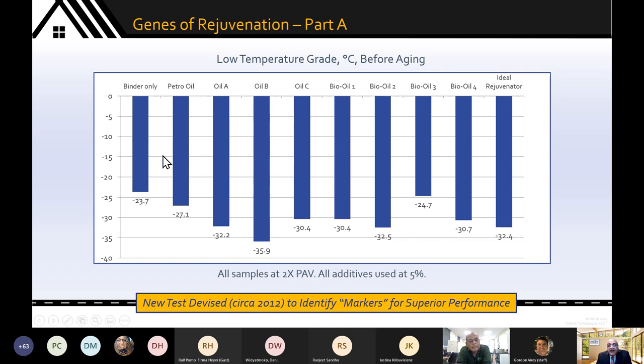So we took virgin binder, we aged it artificially in the lab, PAV aged it to produce synthetic RAP binder. Now we have a highly controlled material to which we added 5% of each one of these oils, just to assess the performance. Right away, you can see that this material is enormously dosage efficient. It gives you almost 2 grades of separation, 12 degrees of separation, just for a 5% addition. And so at first glance, it seems as though this is my rejuvenator of choice.